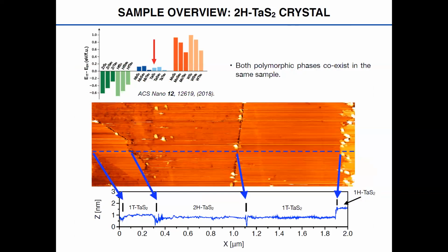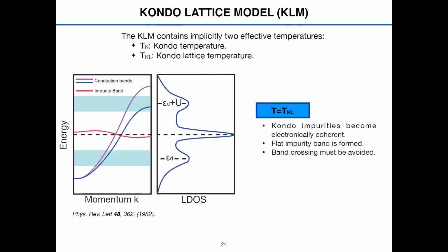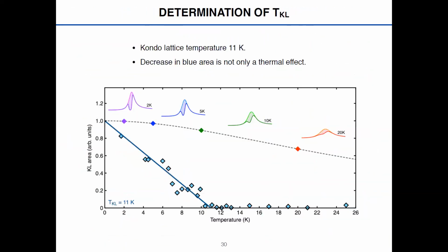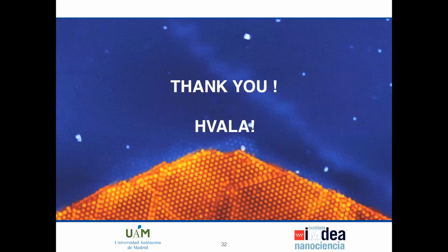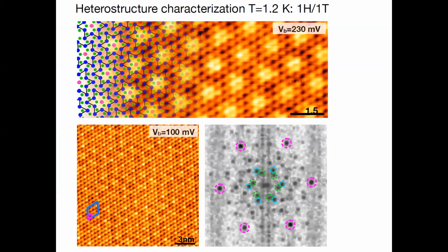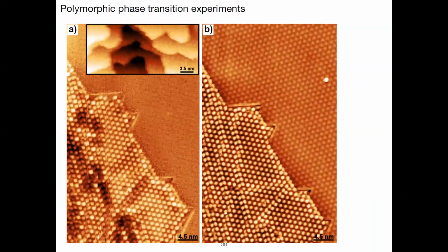Actually, you are able to change the 2H phase to a 1T. This area here is the H, and this is the T. And by doing a voltage pulse, you can change from one to the other. You destroy the area when you do the pulse, but then you can get this polymorphic transition from H to T.